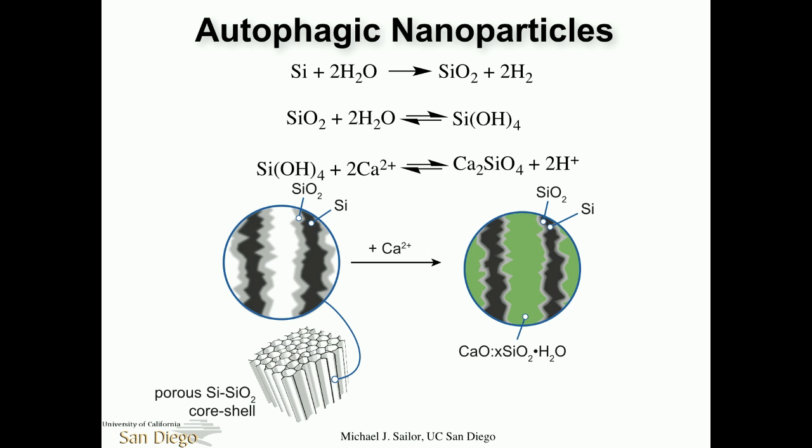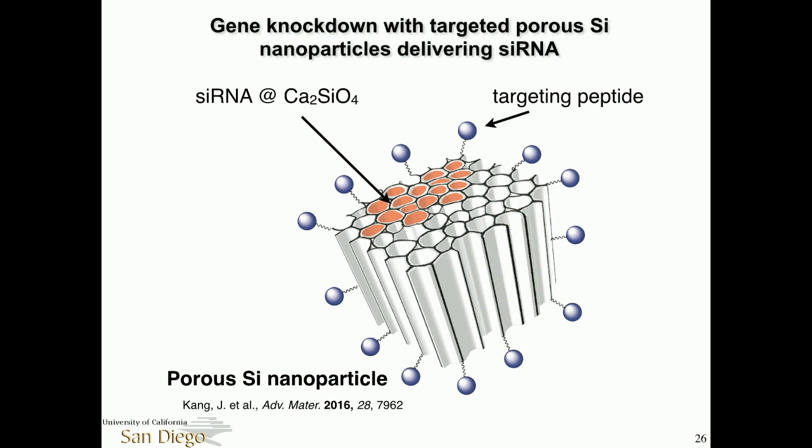Specifically, we take this silicon, dissolve it to silicic acid. If we do it in the presence of high concentration of calcium ion, it forms a precipitate — calcium silicate, which is 80% of Portland cement. So it really does cement things into the pores. The silicon dissolves to make silicic acid, which in the presence of high calcium or magnesium ion re-precipitates as a mixed calcium oxide silicate — a very stable material. It's a good way to recycle the silicon into another type of structure.